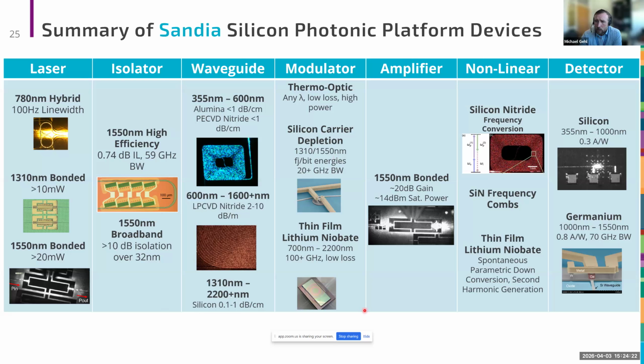Using the same technology as our laser integration, we've also demonstrated amplifiers at C-band. We have a number of different nonlinear demonstrations using both silicon nitride and our integrated thin film lithium niobate. And then on the detection side of things, we have both germanium detectors for telecom wavelengths, and we've demonstrated silicon-based detectors for the shorter wavelengths.